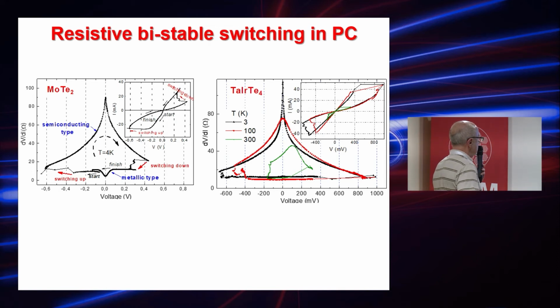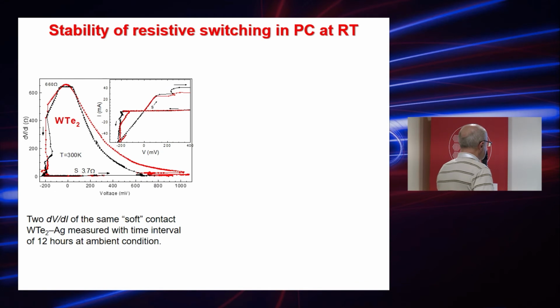Here is an example of another point contact where molybdenum is replaced by tantalum iridium, but this compound has similar properties to the structure of molybdenum ditelluride, and here is shown the dependence of this switching effect on the temperature. We see also that at room temperature this switching effect persists, only this sharp peak is smeared by the temperature. Also, this effect is quite stable.